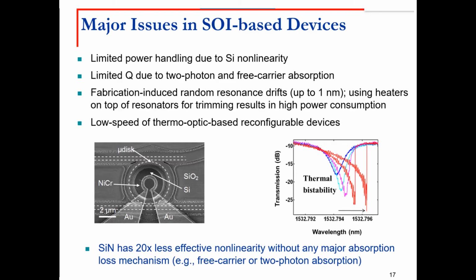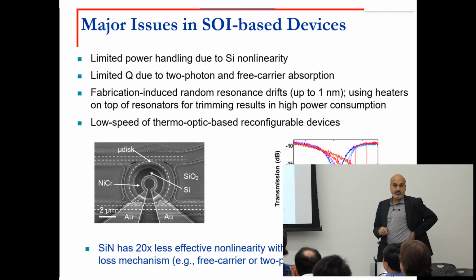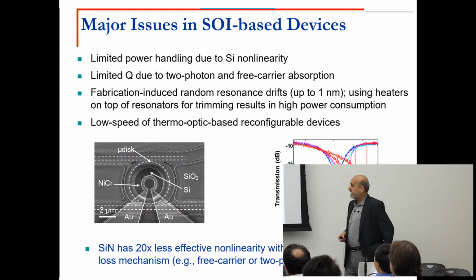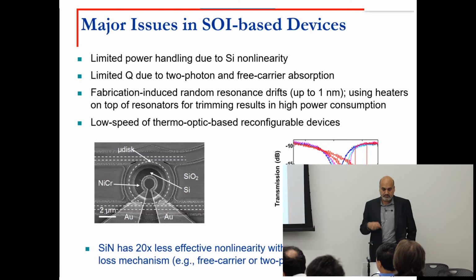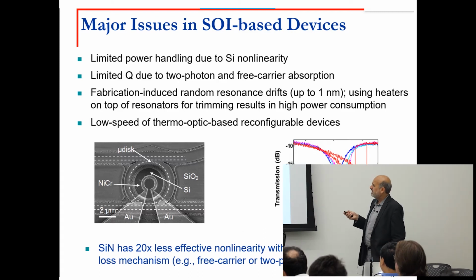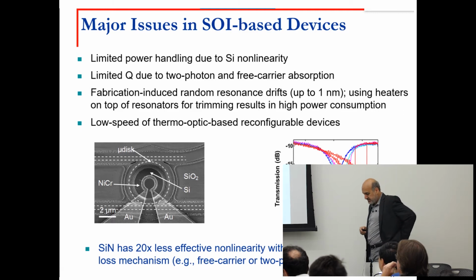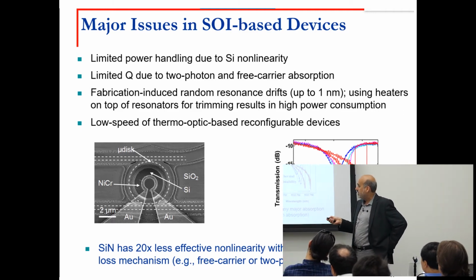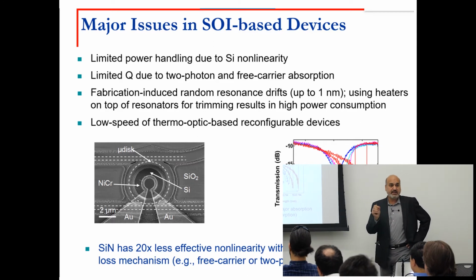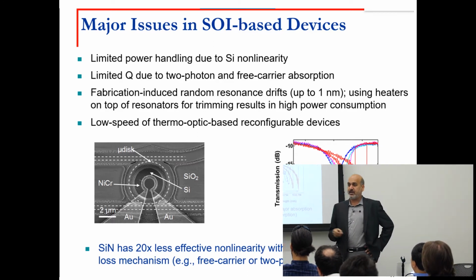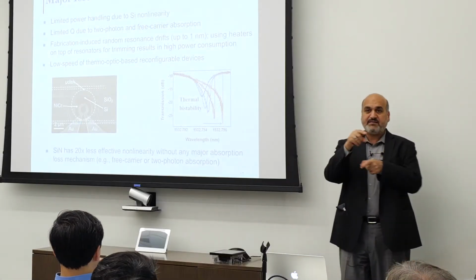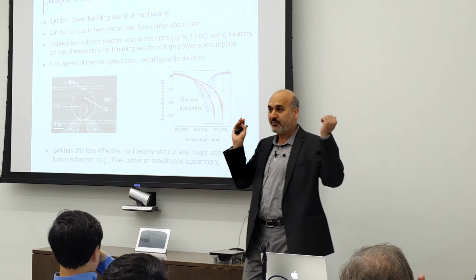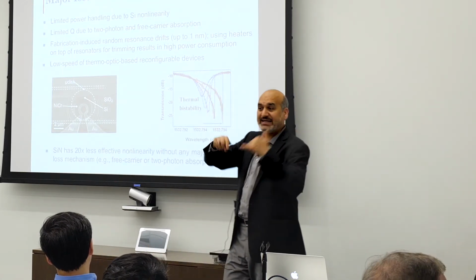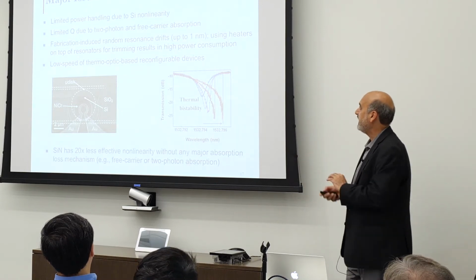Well, silicon is good, but it has its own problems, as I mentioned. Limited power handling due to nonlinearity, limited quality factor due to absorption. So resonators in silicon cannot be made more effective. There are also fabrication-induced randomness in the structures. You form a resonator to be 2 micron in radius, you get a few nanometer error over that micron. That few nanometer error, because of fabrication, will shift the resonance wavelength. It doesn't operate at the wavelength you want. So you have to come back and somehow correct it. So that's another problem that exists for many materials.